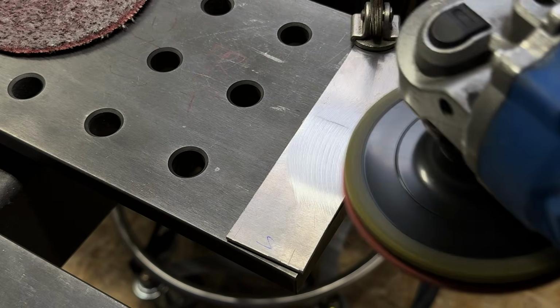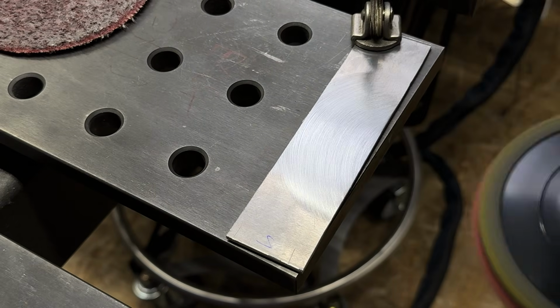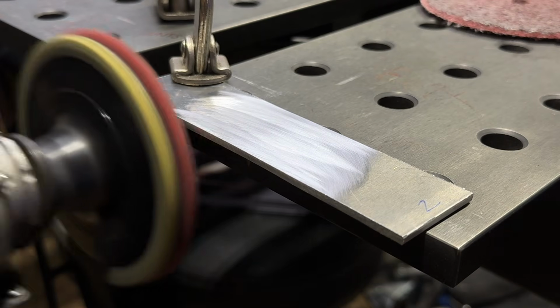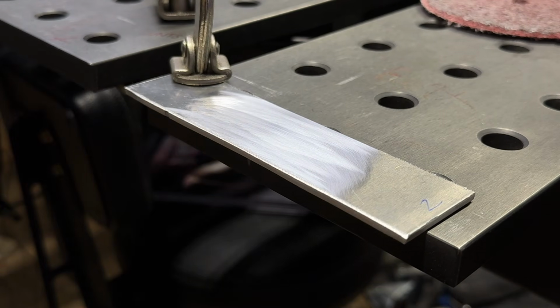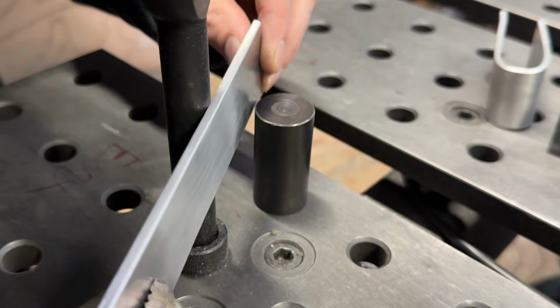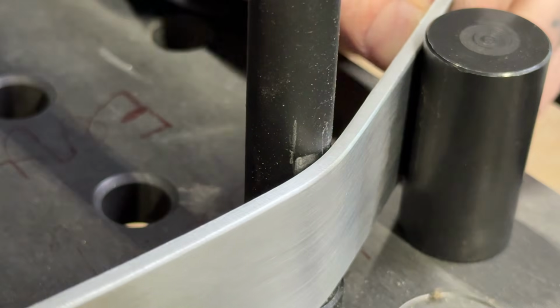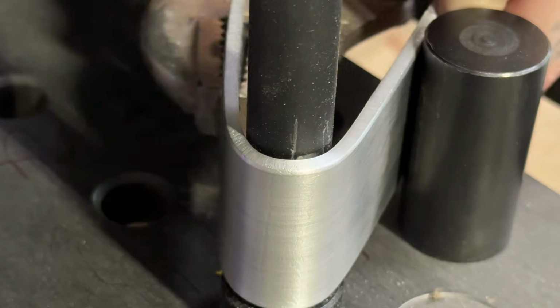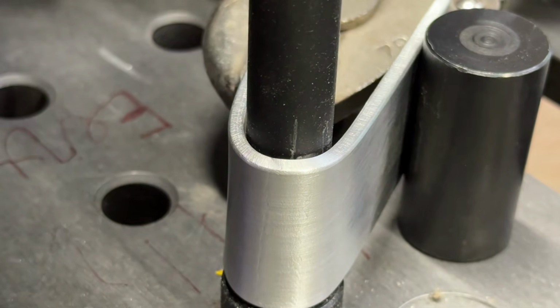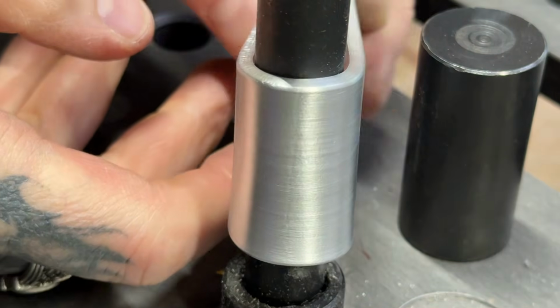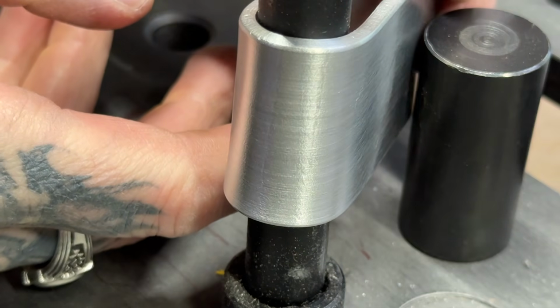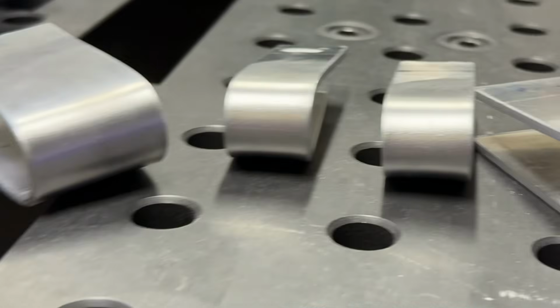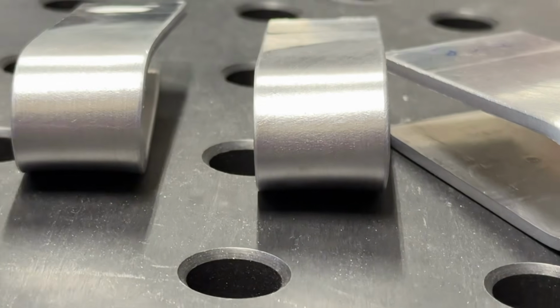But I show in that episode how you can grind them down, polish them down to remove all the welding as well as the penetration and marks from your cutting, and then you can set up a round radius. This one was about 1/2 inch in diameter or whatever, and you can actually do a bending test to see how they hold up. This is a great way to test out how you're doing with your fusion. You can do this very easily with the butt joint configuration with 1/8 inch material, where you can see if you have adequate penetration on the opposite side or not.